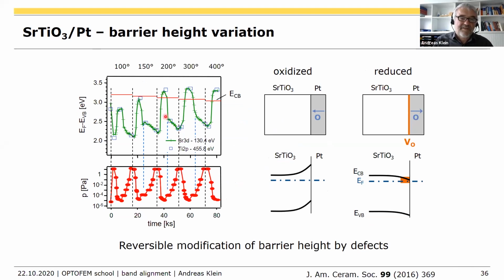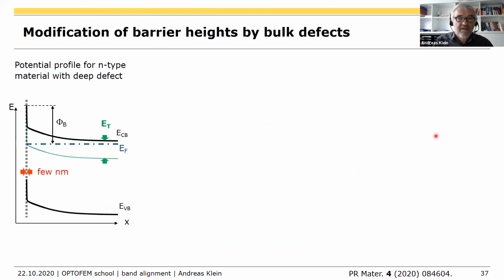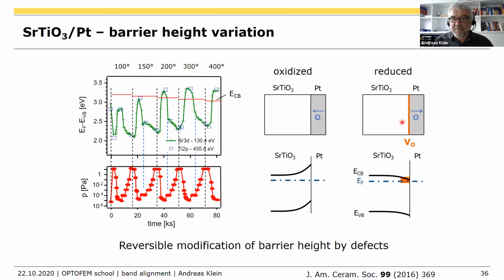Actually, it's only this part where the barrier height is really directly following the pressure. Then if you go to the lowest vacuum, the residual gas, which contains some hydrogen, is really giving a huge change of the barrier. Here you see in green the change of the strontium, and these blue squares are the change of titanium. This is always in parallel. So again, also here, you can shift the Fermi level in principle by more than 1 eV upon oxidation and reduction. That's defects which appear at the interface.